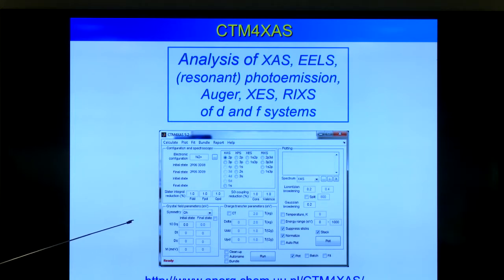And in the new version of CTM4XAS, that's version 6, we interface to this new code, Quanty. And that code is much more flexible and allows you to do a much larger range of calculations. So you can still use the CTM4XAS interface. I always suggest if you're new to start with that, because then automatically you get the spectrum on the screen in a second. But then if you're going to a problem and you have magnetic fields and electric fields and that kind of things, then you should do the calculation by hand, and not use the interface.